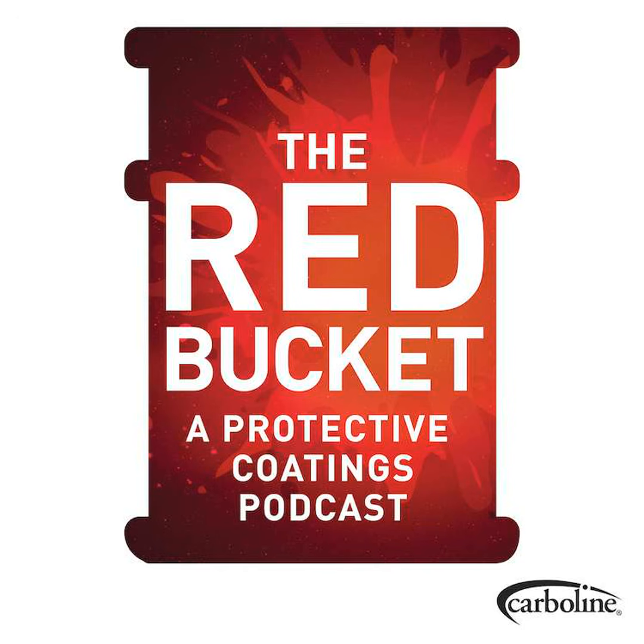Might be a bit of an understatement, but it's quite a destructive test and quite costly. It's like doing a repair job, even when a repair wasn't initially what you signed up for. It's just a fact of the inspection. You're going in blind every time. There's critical parts, like on a piping system, at an elbow or a 90, it's more common to have CUI there than on a vertical run. So there's areas that they can start off with. But yeah, it's very, very costly just to see if you do have corrosion.